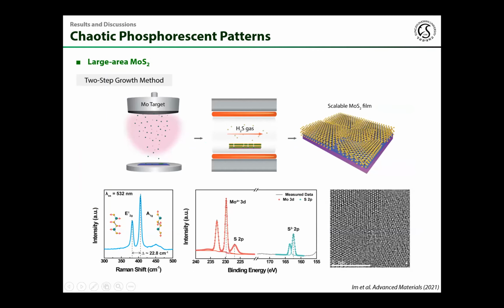Based on this technique, I want to make large-scale chaotic patterns. For that, the two-step growth method is implemented to synthesize large-area MoS2. At first, a few-nanometer-thick Mo film is deposited on the substrate, and this film is fully transformed into MoS2 with H2S gas injection under high temperature.